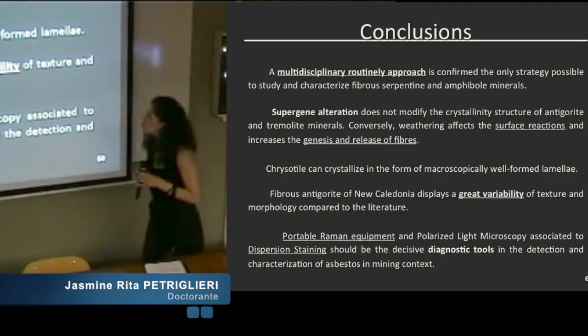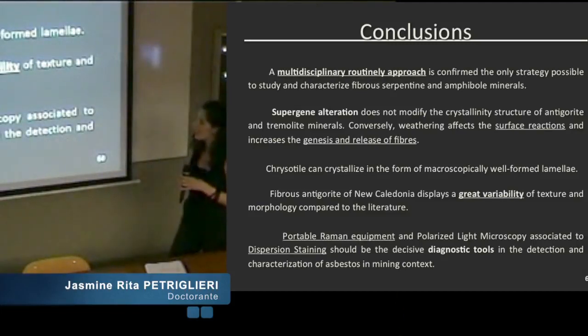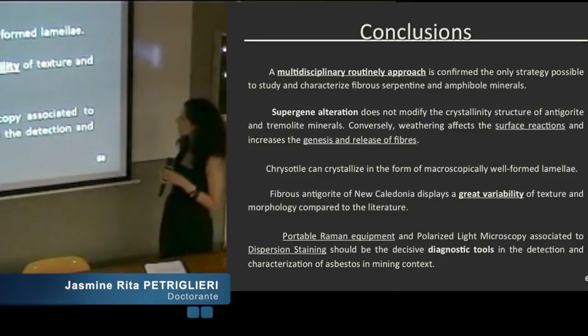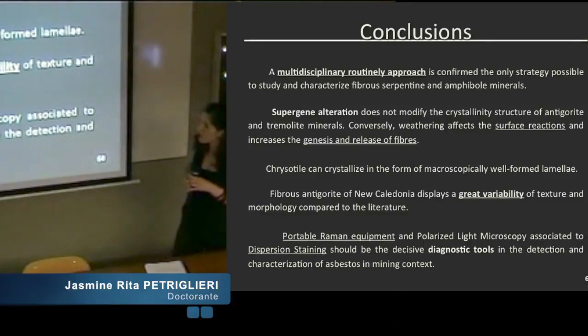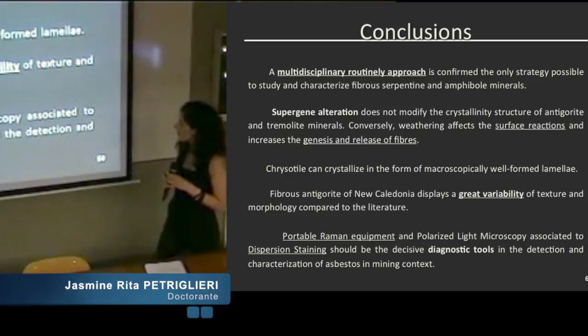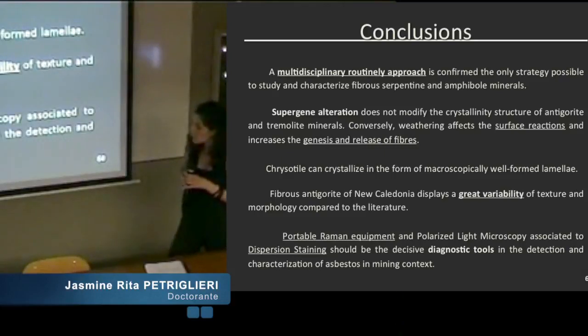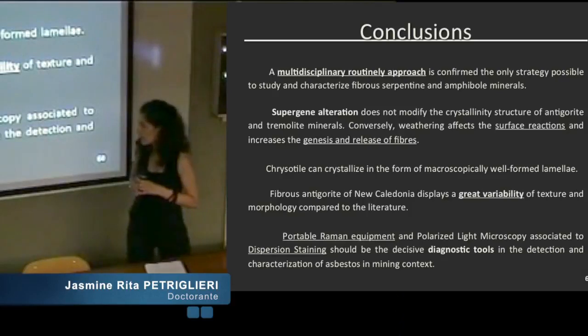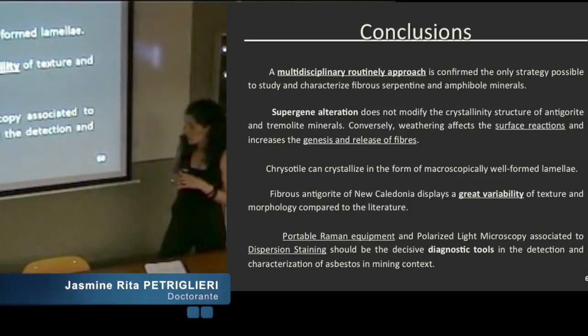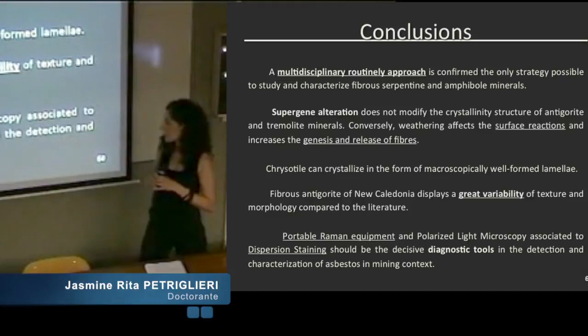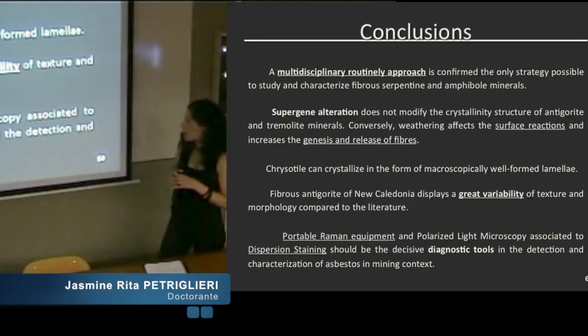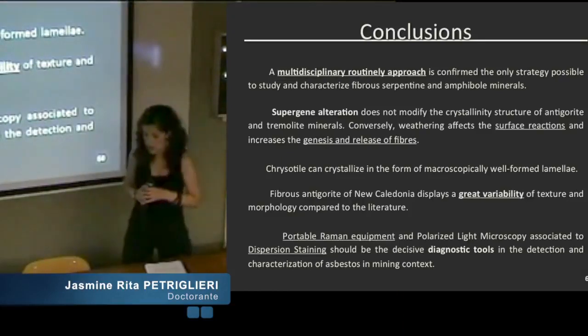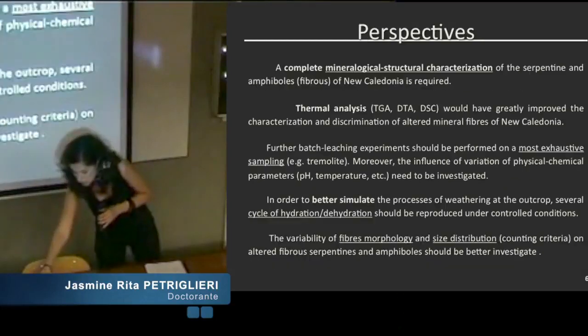It's important to remember that chrysotile can crystallize in the form of macroscopically well-formed lamellae, and the fibrous antigorite of New Caledonia displayed a great variability of texture and morphology compared to the literature. Finally, the portable Raman equipment associated with the dispersion staining observation mode should be the decisive diagnostic tool in the detection and characterization of asbestos in the mining context.